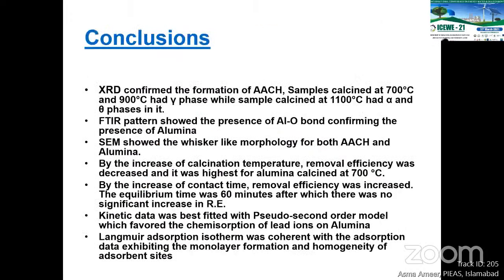In conclusion, we can say that XRD confirmed the formation of AACH. Samples calcined at 700 degrees C and 900 degrees C had gamma phases, while the sample calcined at 1100 degrees C had theta and alpha alumina phases in it. The FTIR pattern showed the presence of aluminum oxygen bond, confirming the presence of alumina. SEM showed the whisker-like morphology for both AACH and alumina.